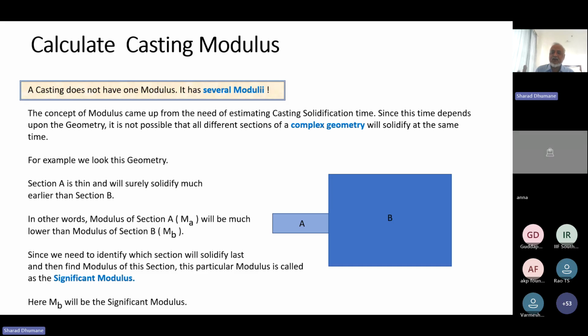So how much later? That is what we apply a 20% factor for when designing the modulus of the riser. If the casting has a modulus of 1.0, we select the modulus of the riser as 1.2. That gives sufficient time for the feeder to compensate all the solidification shrinkage of the casting, provided the riser neck has a modulus of 1.1. Okay.